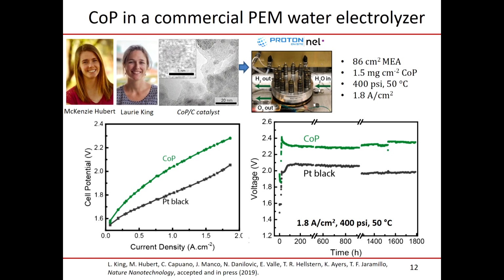And so we, meaning Mackenzie and Lori, prepared catalysts of non-precious metals. We prepared a number of different ones. I'm showing you the example of cobalt phosphide, high surface area formulations. We shipped them off as a powder to Connecticut. We're not allowed to know the secret sauce that they used in making these things. They pretty much took their normal preps as if it were platinum and integrated it into their cells. And what you see is it performed extremely well. Again, you see it's driving 1.8 amps per square centimeter. And again, you're paying that 0.2 volts, which is exactly what we expected based on the slower turnover frequency of non-precious metal catalysts. What about the stability?